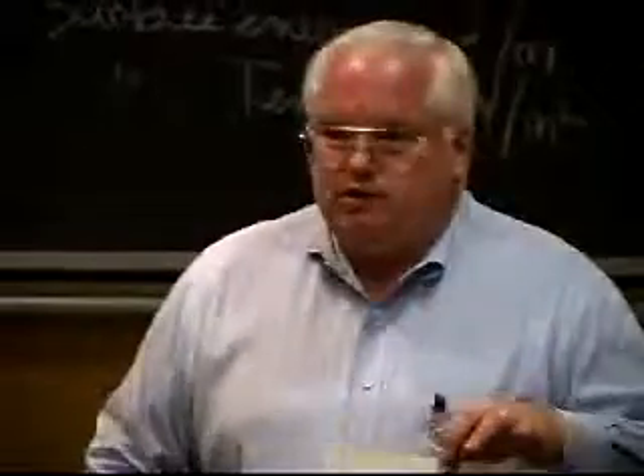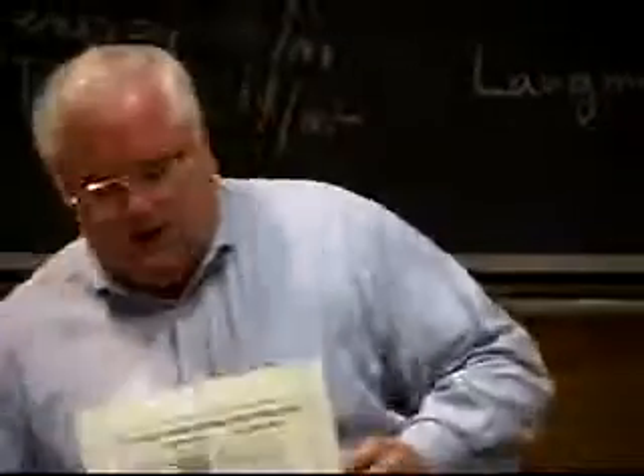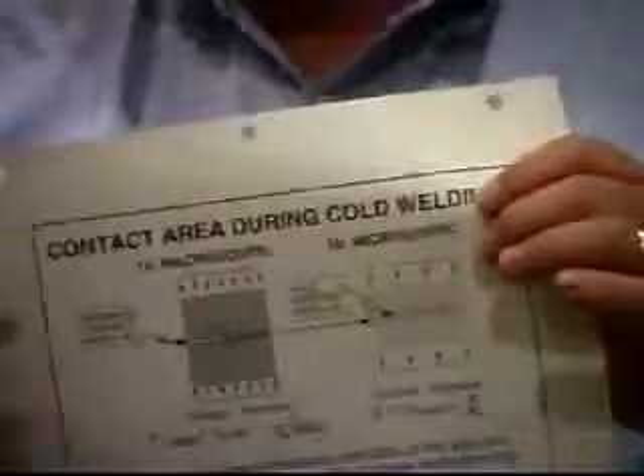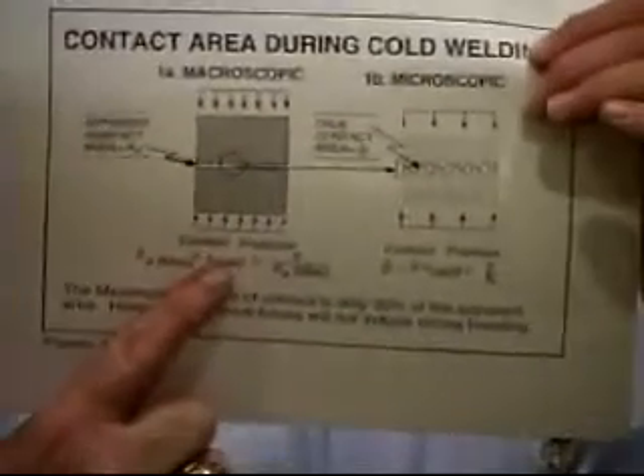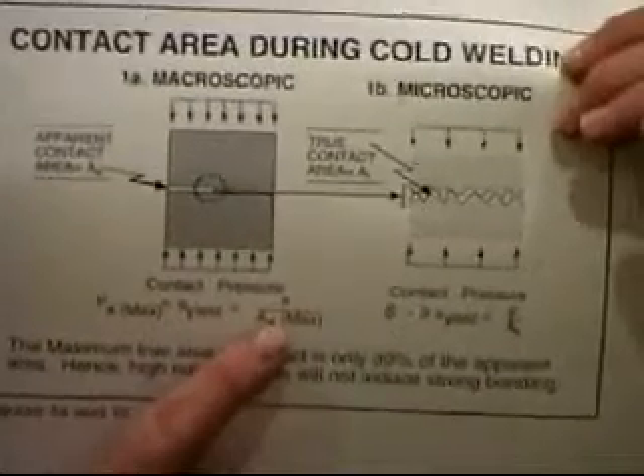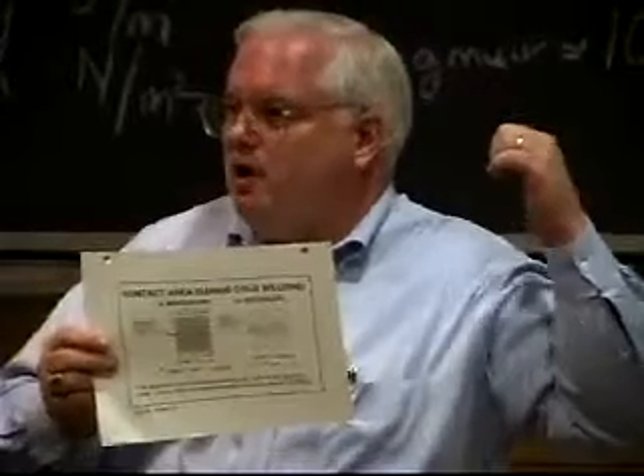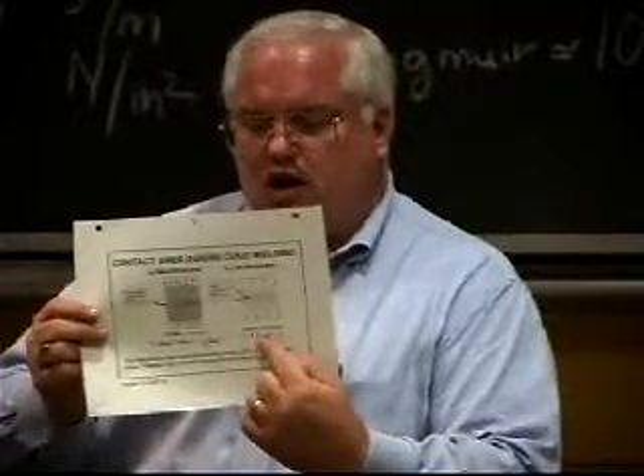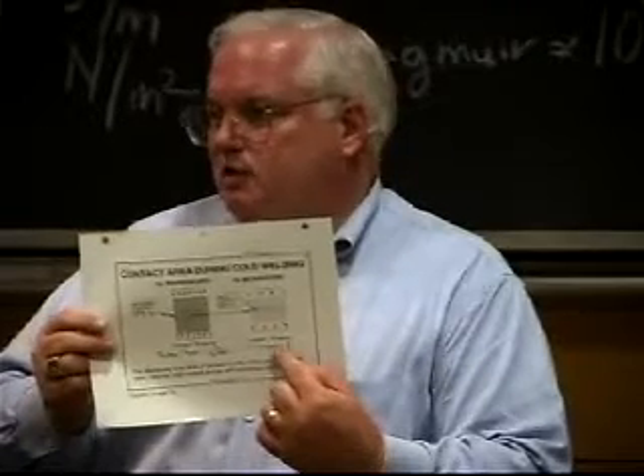Essentially, what I've then done, using that type of knowledge, here's a copy of the contact stresses that we're talking about. If I were to study the thing on the top there, macroscopic deformation of 2 solid objects, I would find that the load applied, P over A max, is equal to the yield stress, which is just the force divided by the area. And that's the macroscopic force. If I now look on a microscopic scale, where I actually have asperity contact, I know what the force to deform those asperities is. It's close to the hardness test. And so it turns out the average pressure is going to be about 3 times sigma yield, or S yield. Okay?